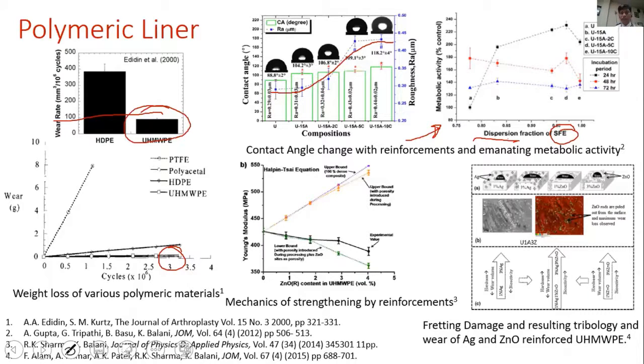Then again, we can play with strengthening, because essentially it is the life of this particular acetabular cup liner. So how can we bridge that gap of higher hardness of the ceramic femoral head versus lower hardness of the liner? And then we can also see if we can attain some added functionality. I can get higher bioactivity by adding zinc oxide, and also good antibacterial activity by adding silver. But that may also have some repercussion on the tribological response. I can also see fretting or pin-on-disc type of wear, and that part I will highlight later on.